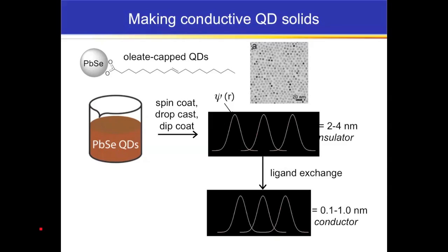We make a film in some fashion by drop casting or dip coating in some way. And what we end up with is a material where, you can't see it, but these should be quantum dots right here. The idea is that the spacing between the dots is set by this long insulating ligand here, and it's significantly longer than what one would need to actually get good charge transport. And so you basically have an insulating material because the wave function overlap is essentially 0.